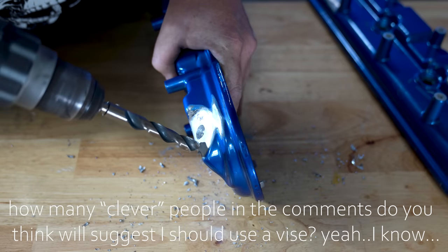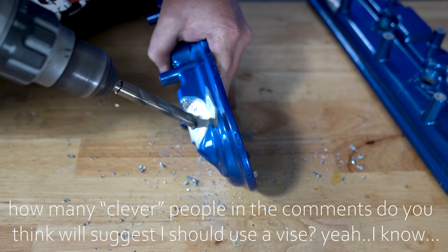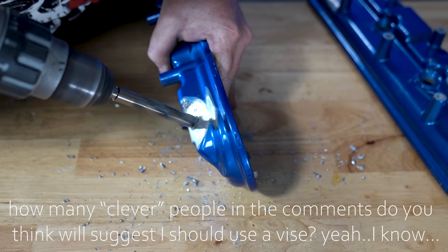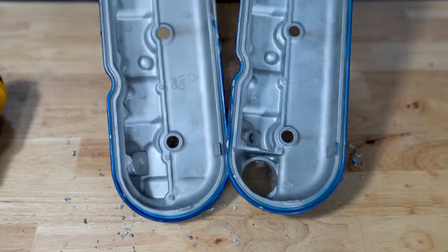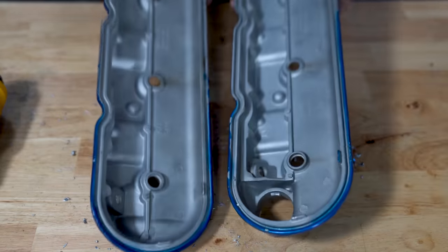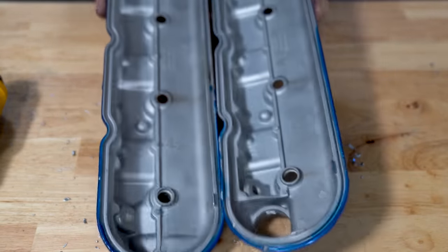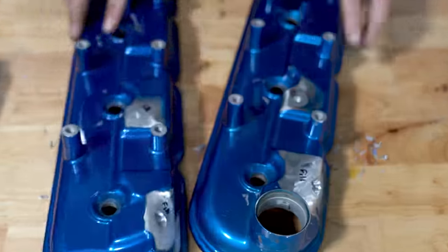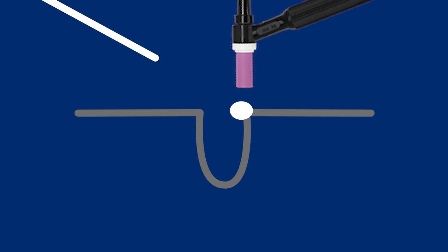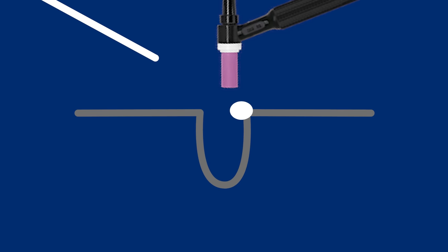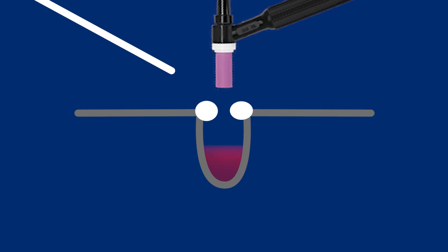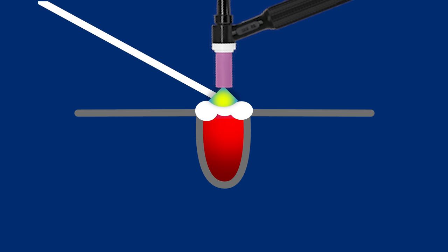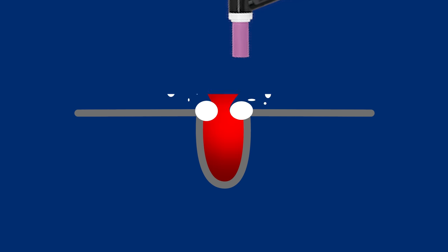The one step that I'm going to leave out for demonstration purpose is relief drilling. These bolt holes are blind holes, which means they do not go all the way through the valve cover. When you try to weld over a blind hole, heat will build up within that cavity. Heat in enclosed spaces creates pressure, which has to go somewhere. 99% of the time, that somewhere is right back out of the cavity through the molten metal that you are trying to fill it with.